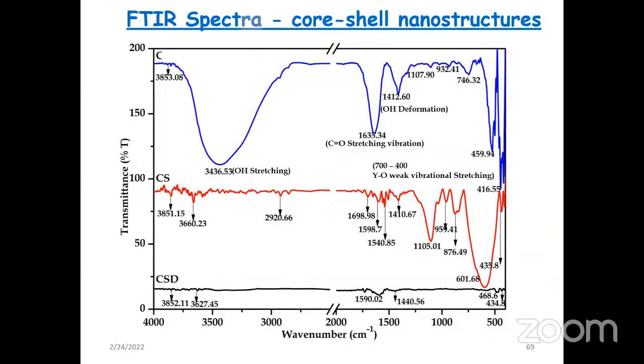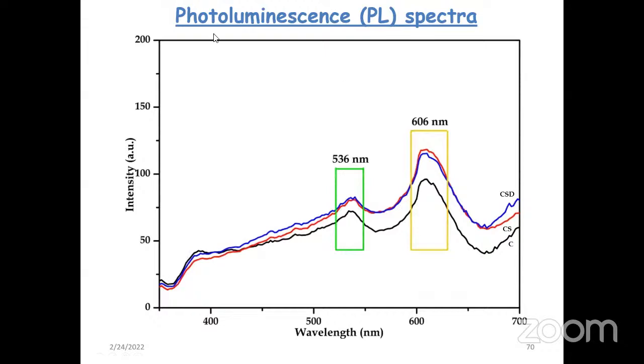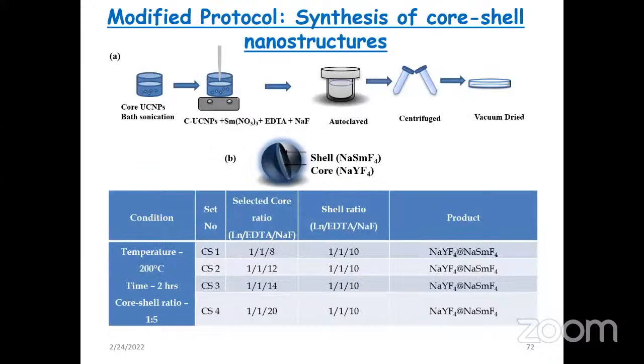We studied this by other characterizations as well. We subjected it to photoluminescence spectra, where we could find that with dopant or without dopant, they produce a similar level of photoluminescence effect. Further, we subjected the core-shell nanoparticles to HRTEM with EDAX to identify whether it has all the components. We could confirm the presence of sodium, fluorine, samarium and yttrium. This is the core-shell doped, where we also have erbium and ytterbium, so Er as well as Yb are present. This clearly indicates that all the components were incorporated in the upconversion nanoparticles.